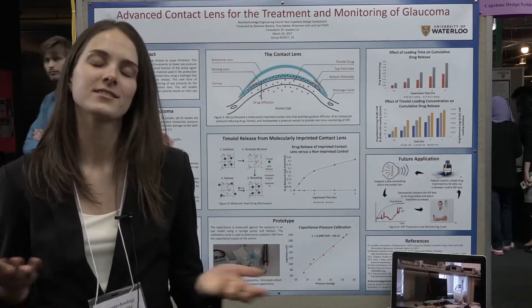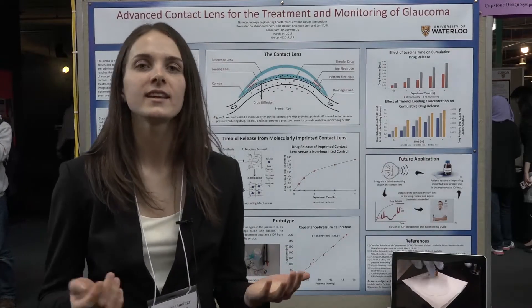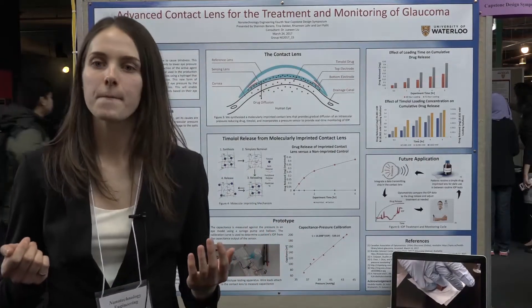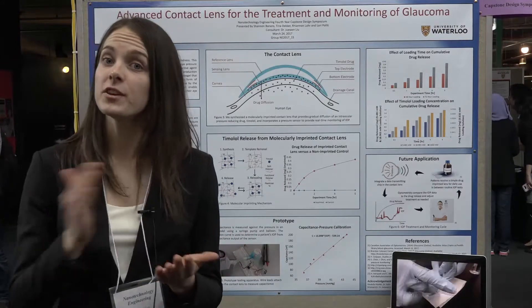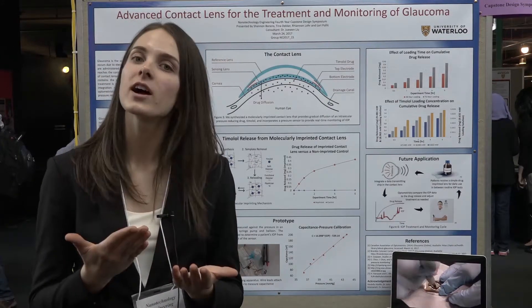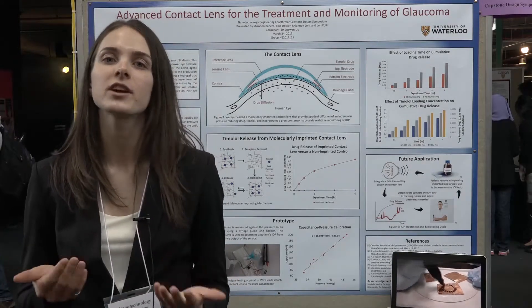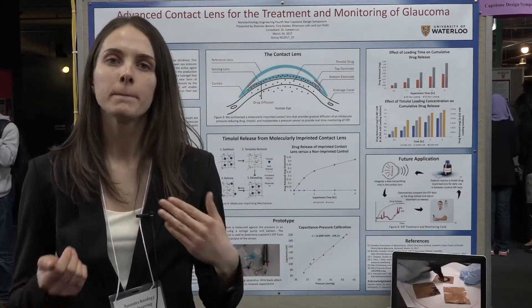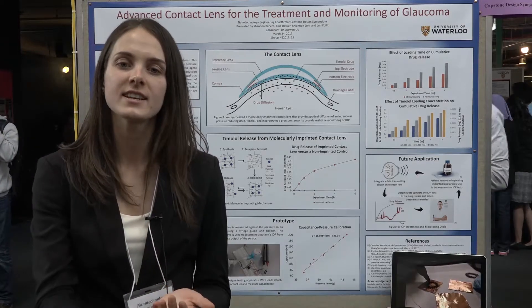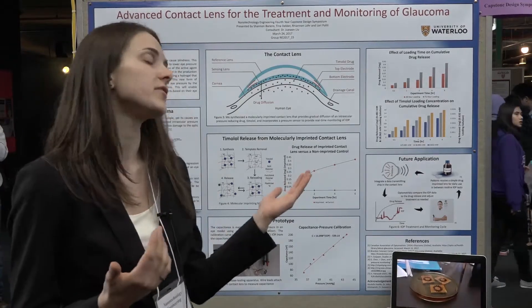We did this for both layers, except the top layer didn't have the plasticizer or the drug, as it's not needed. What's great about this contact lens is that the drug delivery can be tailored. We found that we could tailor the diffusion time based on the nature of the polymer network — by making it more cross-linked, it has longer diffusion. We can also tailor the drug dose administered to the patient by increasing the concentration in which the contact lens sits to load the drug.